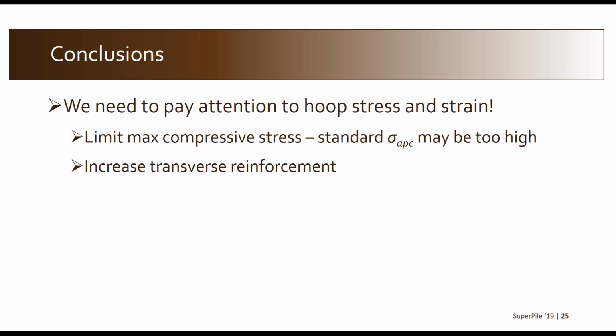We should also be providing enough transverse reinforcement to handle these loads as was recommended in the PCI report. I think that's pretty straightforward. And avoid driving these things completely underwater. They're often vented if they're going to be driven close to the water, and that's certainly recommended. But I would completely avoid driving them when they're full of water because the water hammer effect could definitely lead to a failure.